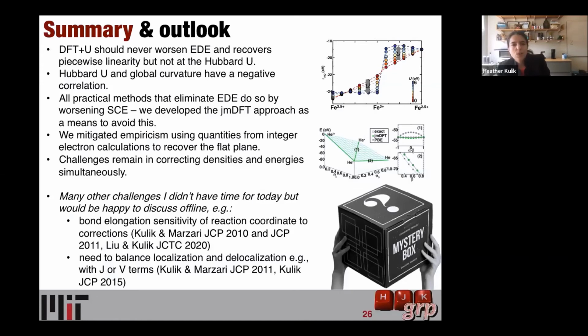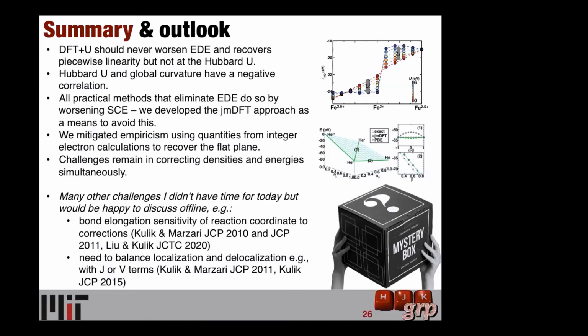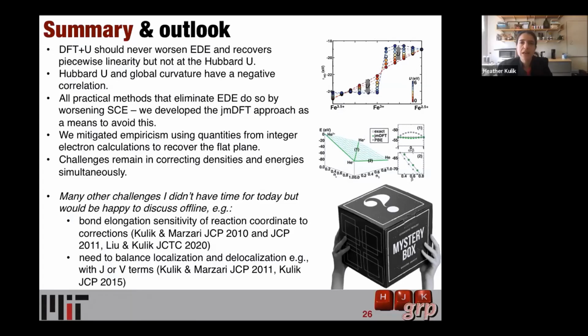I think it's one way to think about what is neglected in DFT+U. We have moved much more to the perspective of either the occupation matrix detects what you want to detect or it doesn't. The V is, I think, an approximate way to get back to detecting more things in the occupation matrix. But these other approaches popularized by a range of people, including, say, putting a Hubbard U on the P states of the nearby atoms might be preferable. I think they're all getting at the same thing.